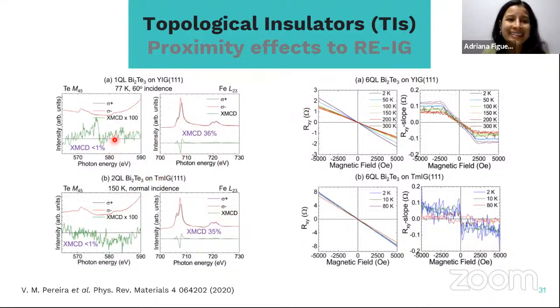And then they also saw that there's no XMCD on the tellurium atoms, for example, for this kind of system of bismuth telluride interface with YIG or with TmIG, just as what we do, but they do see some induced or proximity effects in transport measurements. So there is an incompatibility here: how can we reconcile these two results? So it's important to know what happens here.